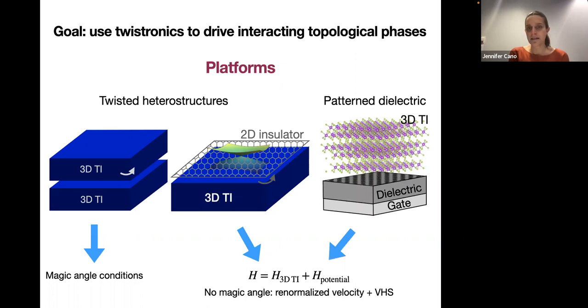And then finally, there's a third idea, which I really like, which is, what if we take our 3D TI and put it on top of this setup? So we take some dielectric material and punch a bunch of holes in it in a regular pattern, and then put a gate underneath. That way the 3D TI surface will feel the gate in a spatially modulated way. And that will also have the effect of having some large scale potential on its surface. So these two approaches, physics-wise, experimentally wise, are very different from each other. But theoretically, they're doing the same thing, which is they're imposing a periodic potential on the surface of a topological insulator.